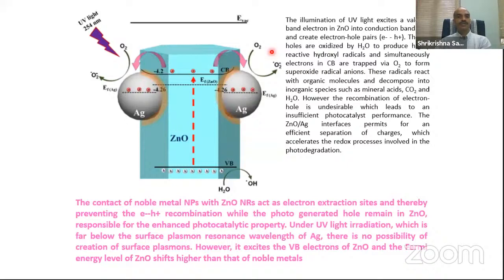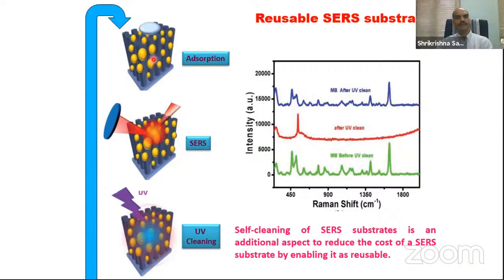However, you should see that this UV light, because it has very high energy, will not cause any plasmon resonance, so this will not disturb anything. Only those probe molecules which are adsorbed on this surface will get degraded. And then what will happen? Yes, I can now adsorb again. For example, these are metal nanoparticles coated on zinc oxide or TiO2 or whatever oxide nanostructures. Then these probe molecules will be adsorbed.